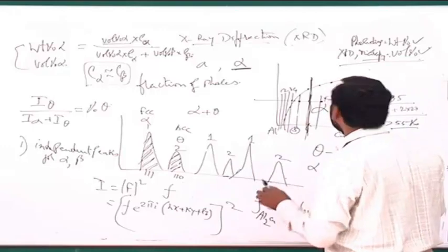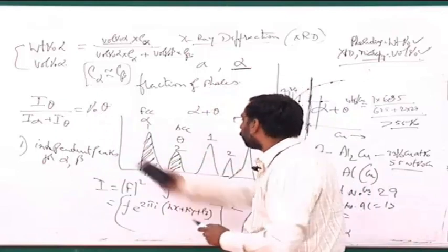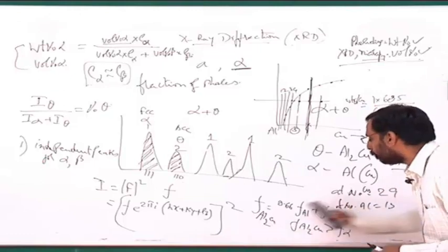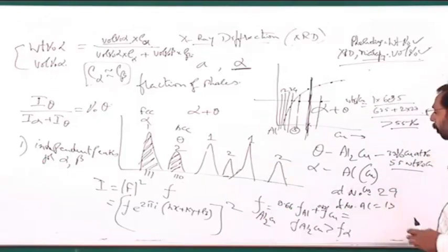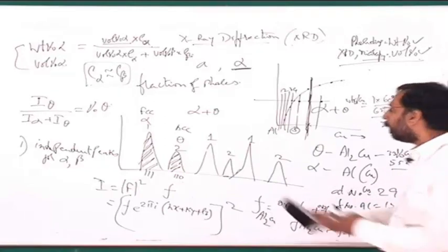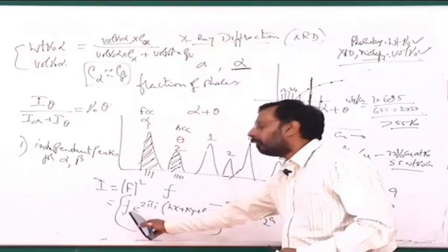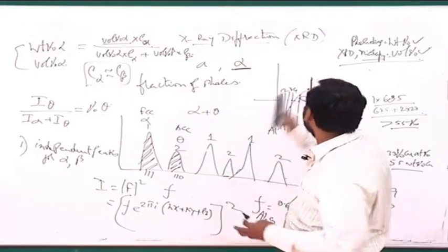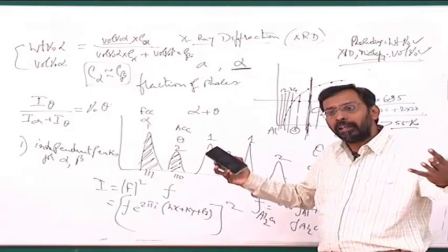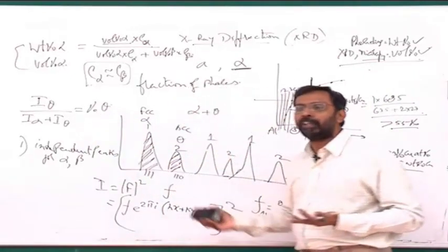So knowing this problem, I need to first find out the amount of theta from the XRD pattern, and make sure that the structure factor is considered. In principle, because the structure factor of Al2Cu is higher than the structure factor of alpha, the Al2Cu peak will be bigger because the intensity is the square of the structure factor. So this peak, though it is supposed to be only 15%, shows as if it is 30% or 40% maybe. So by simply calculating the ratio, you may get 30 or 40, but the actual amount is only 15%.